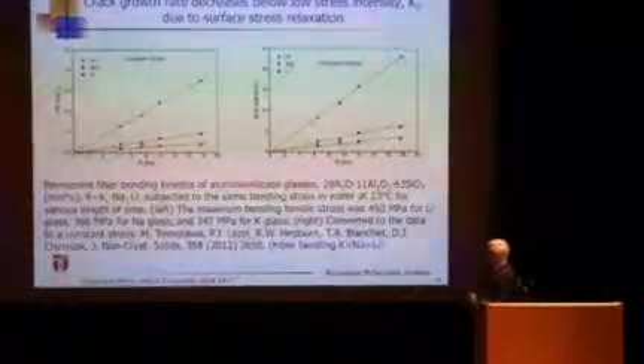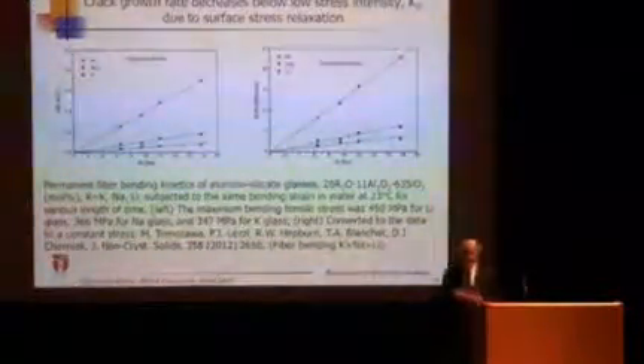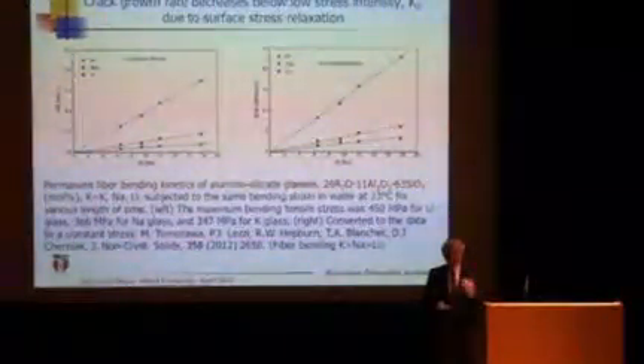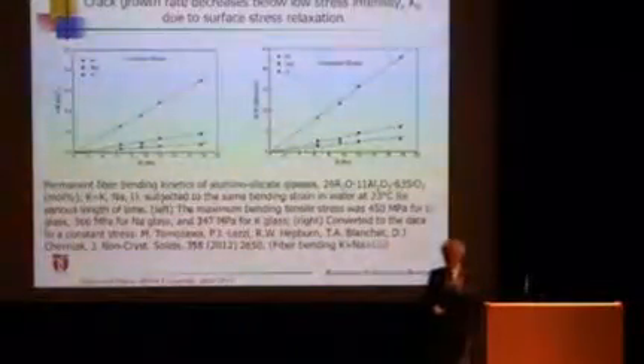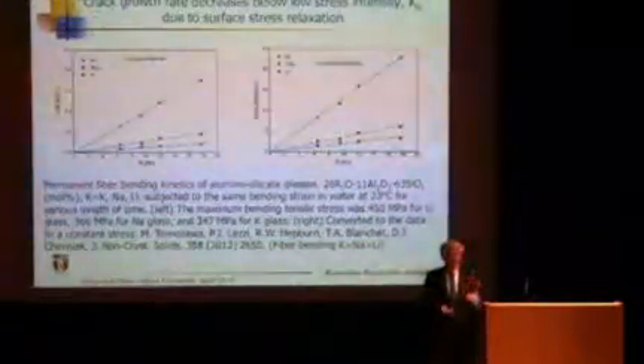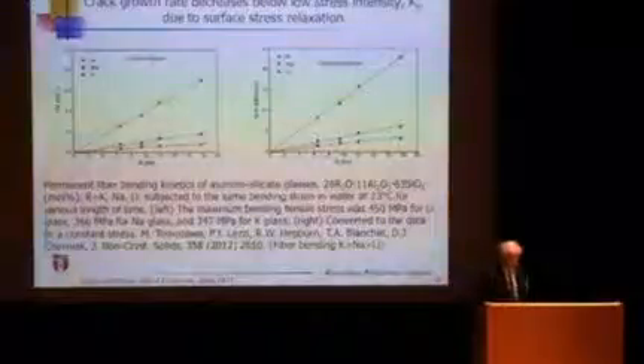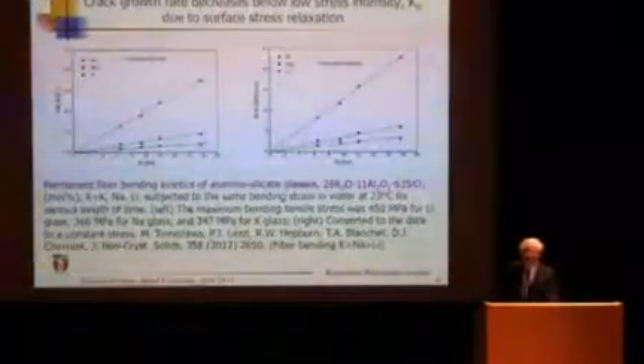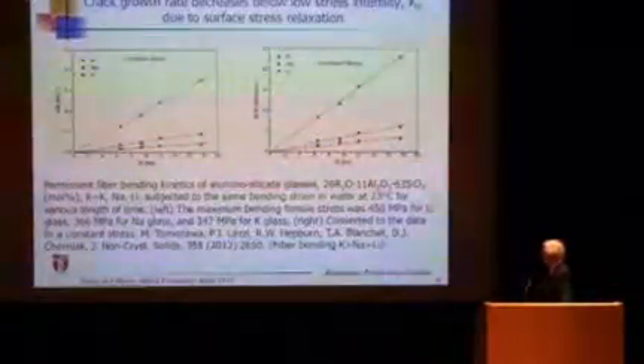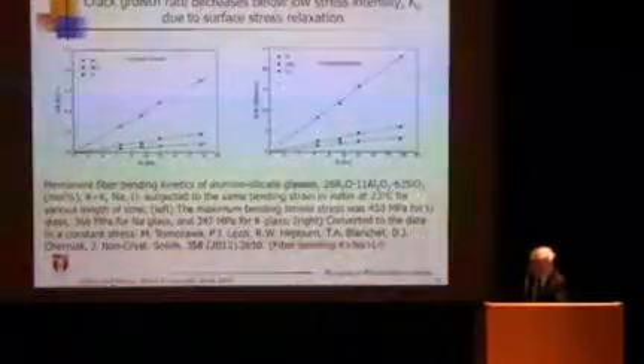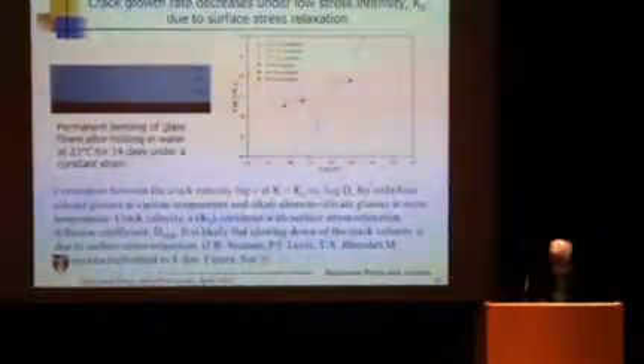That potassium glass has a faster surface stress relaxation, and that glass is the fastest to show the fatigue limit under higher stress intensity. So qualitatively, we think we are on the right track. And this trend can be shown in this manner.